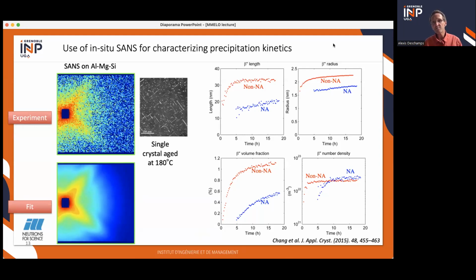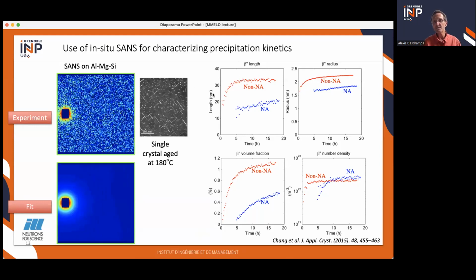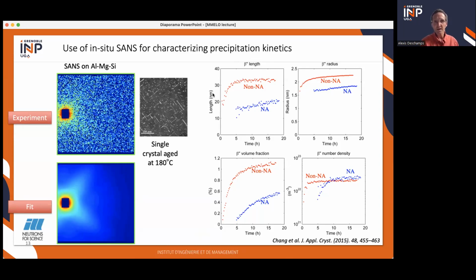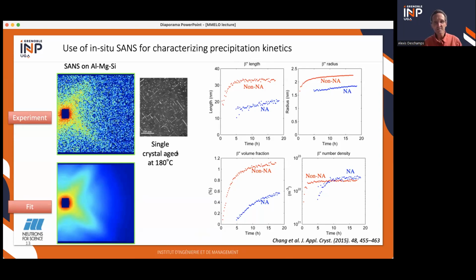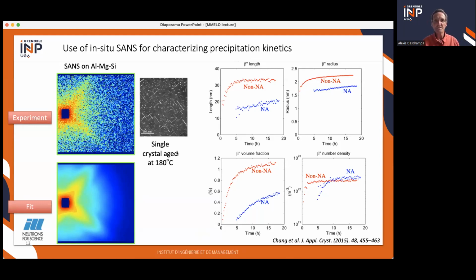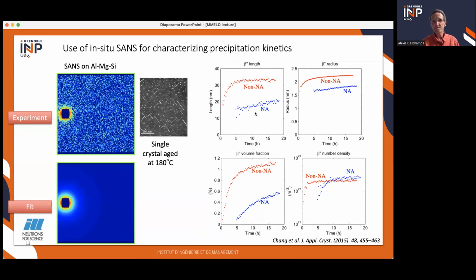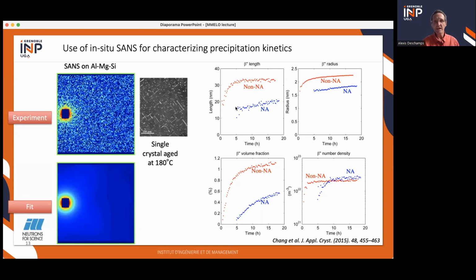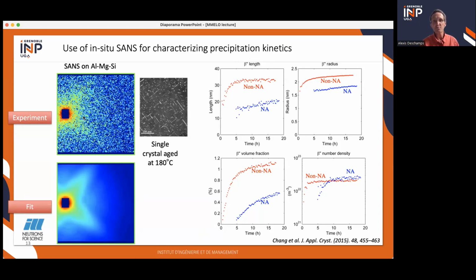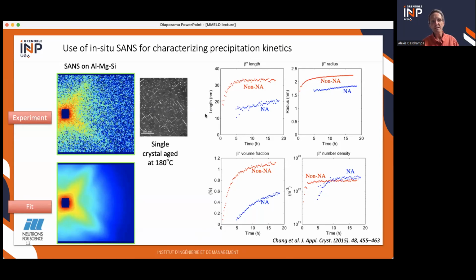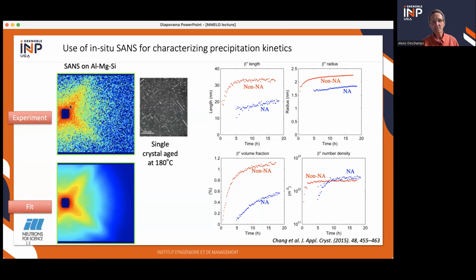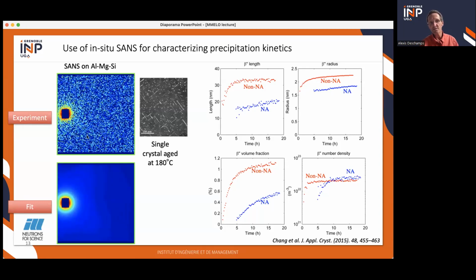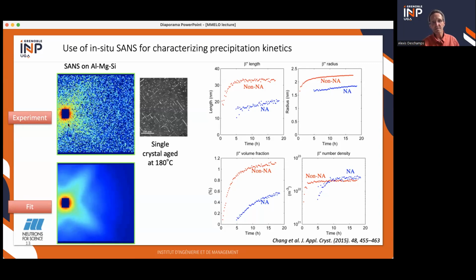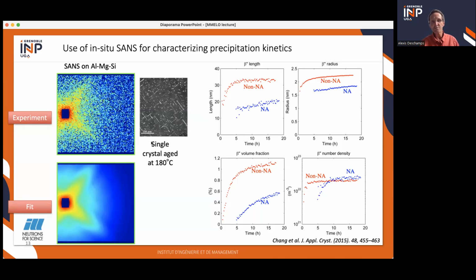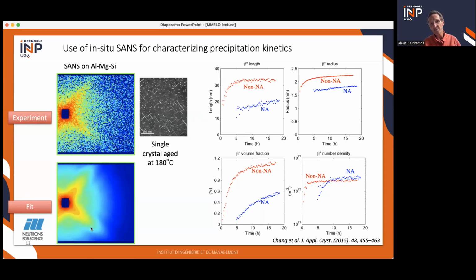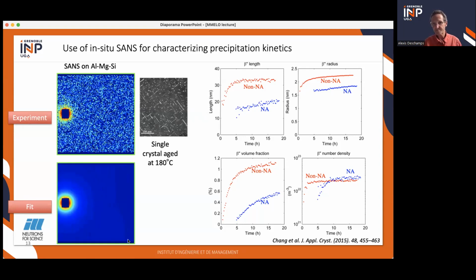And so these beta double prime particles, which are quite the classical hardening phase for automotive aluminum alloys, are very sensitive to the prior presence of natural aging. And here, these experiments were done in situ and gave all the parameters of the particles due to the fact that you're in a single crystal and that you can model completely the SANS signal from these different variants of the precipitates, which gives you this anisotropic signal.